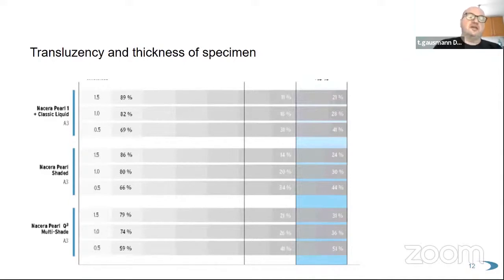So here you can see the specimen thickness: 1.5 millimeter, 1 millimeter, 0.5 millimeter. You can see here the opacity of the material. This is Nacera Pearl 1. It's a white disc colored with normal classic liquids like we have our own, or zirconzahn liquid or something, then you can imagine what it is. Here you've got Nacera Pearl shaded. It's a pre-colored monochromatic disc that is A3 from top to bottom. There is no translucency added, no transition in translucency. It's just A3 dentin, that's it.